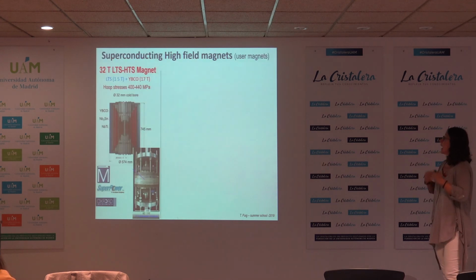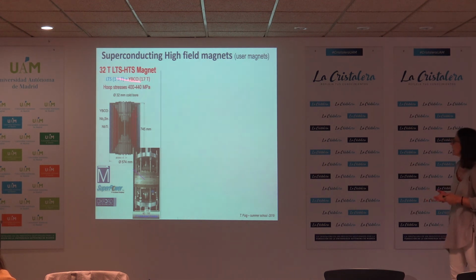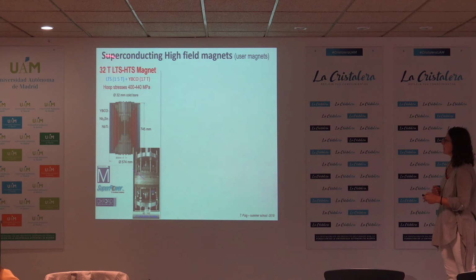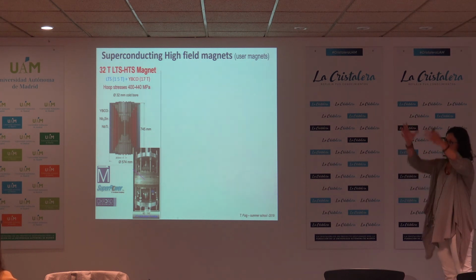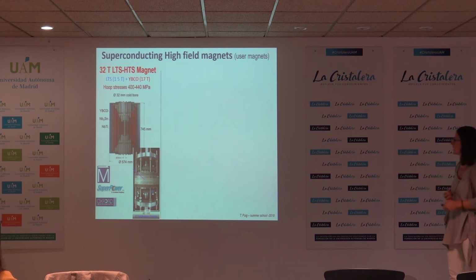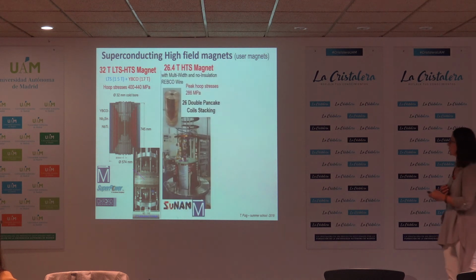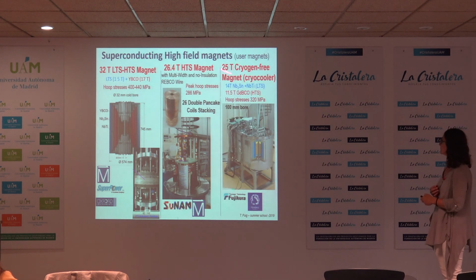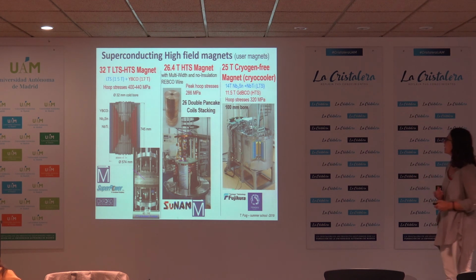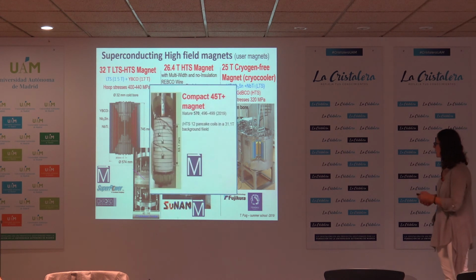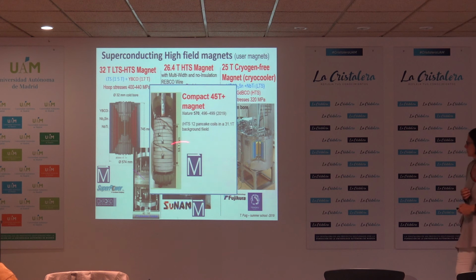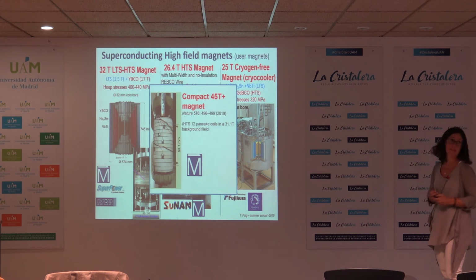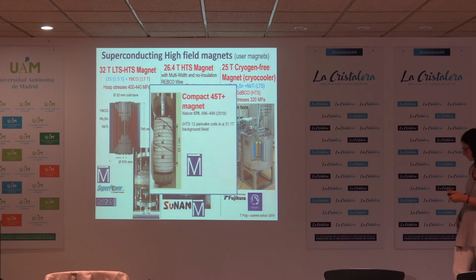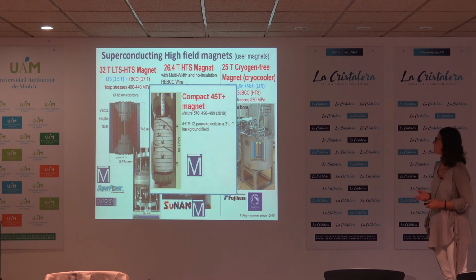HTS magnets. In magnets, it has now been demonstrated, for example in Tallahassee, that we have 32 Tesla magnets because of the DC, because of the LTS plus HTS. So the idea here is always that you use niobium tin, niobium titanium, and then the HTS, and each one is summing the magnetic field. So they have demonstrated this 32. Also in Korea, they could demonstrate a 26.4 all HTS. Also in Japan, 25 Tesla with the niobium tin, niobium titanium, and gadolinium BCO. And the latest news in Nature is that Tallahassee has been able to get a compact 45 Tesla DC magnet with the HTS. So this is also going on.